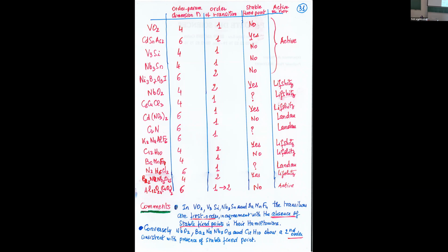the Lifshitz condition is not fulfilled. Then it opens a new mathematical field, because here you have to minimize an integral, since you have to introduce in the free energy a gradient term, also a Ginzburg term, the second degree of the derivative. And then people began to ask how to solve such an integral by the Euler-Lagrange equation. So it was a big fashion, I would say, between the 70s and the 80s, about incommensurate phases. Also, people began to find more and more incommensurate phases.